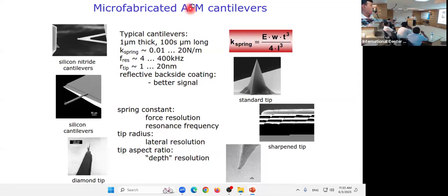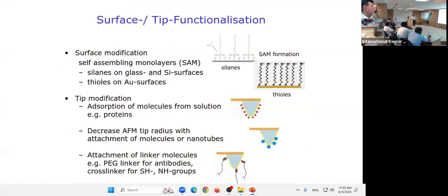So that is what is important, if you want to have a better resolution. And normally the back side, like this is the upper side, but this is the cantilever. You see, so this is the radius, and this is normally prepared from silicon nitride. So if this is thinner, you will get better resolution, but it can break easily, and that's the reason that initially we used a bit thicker cantilever surface.